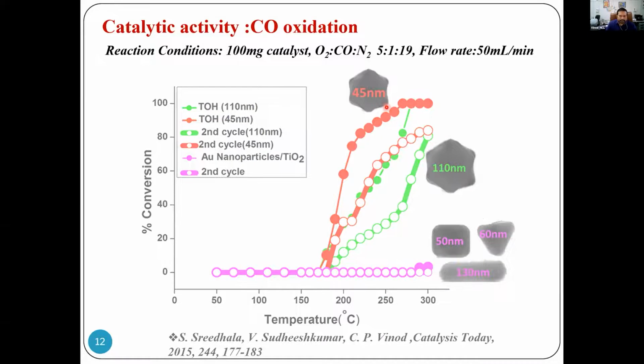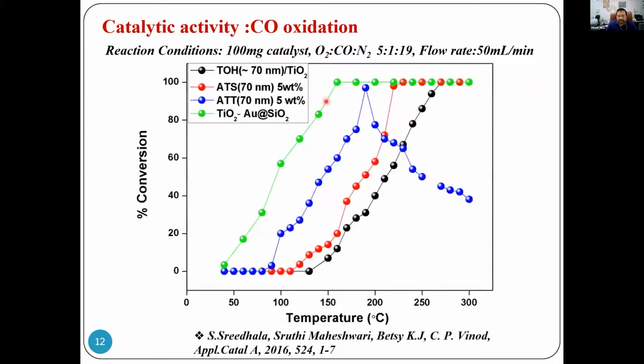CO oxidation. This is the inverse model catalyst that we made, where you are trying to support it with TiO2, and you can see that it starts to show activity close to room temperature. And around 50 to 60 degrees Celsius, you start seeing carbon monoxide getting converted to CO2.